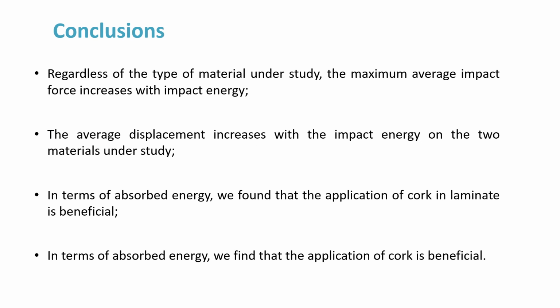Conclusions. Regardless of the type of material, the maximum average impact force increases with impact energy. The average displacement increases with the impact energy in the two materials under study. In terms of absorbed energy, we found that the application of cork in laminates is beneficial.